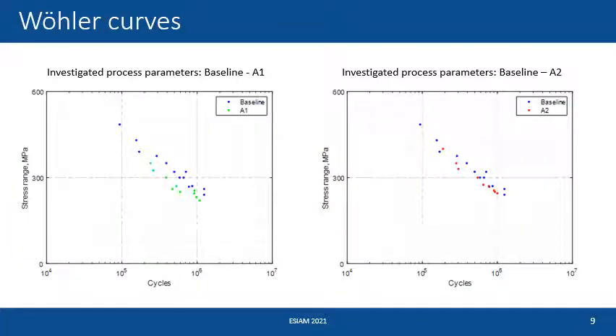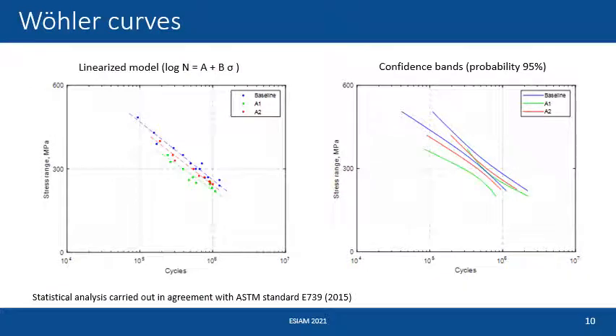But if we move to analyze the fatigue behavior, we see that in spite of the increase in porosity, the fatigue response of the specimens produced by using the productivity-oriented process parameters is almost coincident with the specimens produced with the baseline parameters. In particular, for the A2 parameters, we see that the data are almost coincident. We represent the three datasets on the same figure, and we introduce the standard statistical analysis approach conventionally used in the high cycle fatigue test analysis.